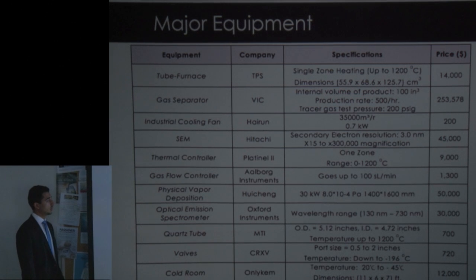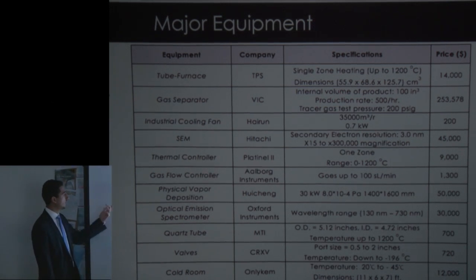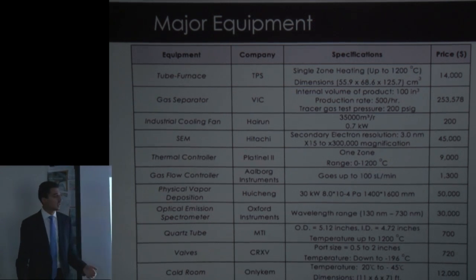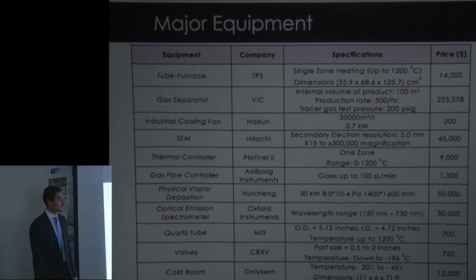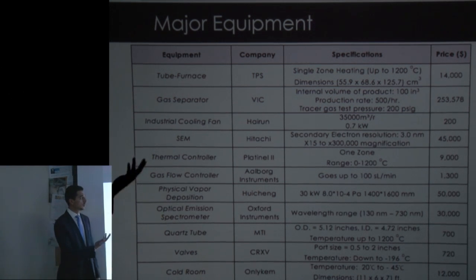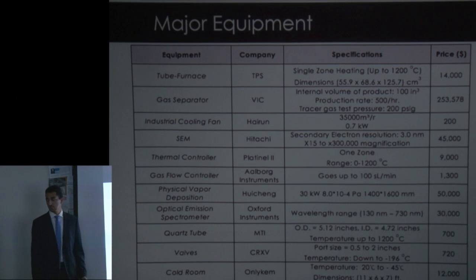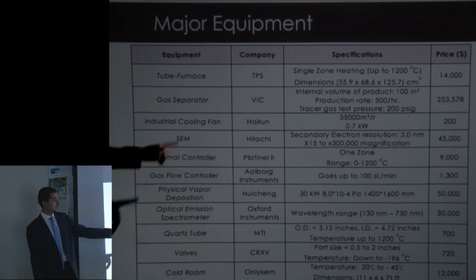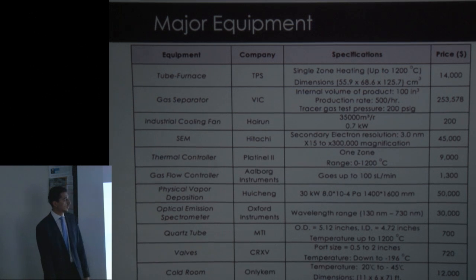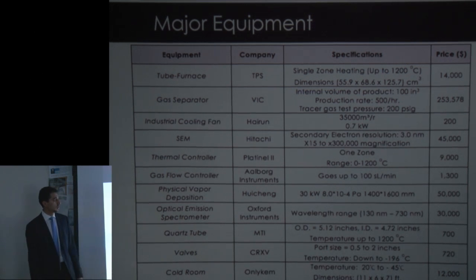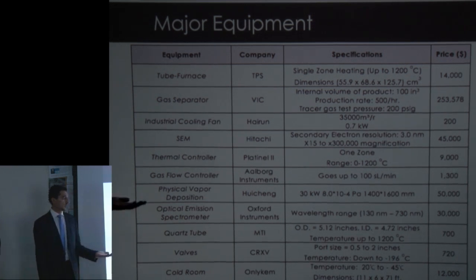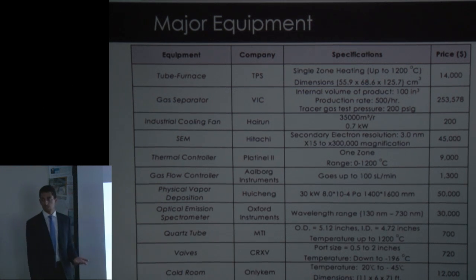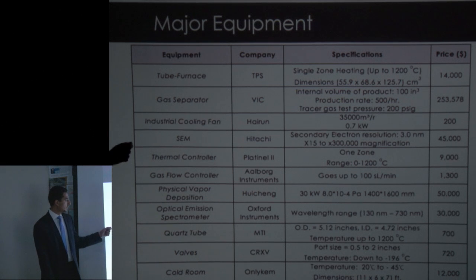So for our major equipment, here's a quick list. First is the tube furnace, which is the CVD reactor. We're using a single zone heating, which reaches up to 1200 degrees Celsius. Its cost is around $14,000. We have the gas separator. You could see it took a lot in terms of our installed capital cost. After we have done our calculations, the gas separator proved to be beneficial, and economically beneficial as well.